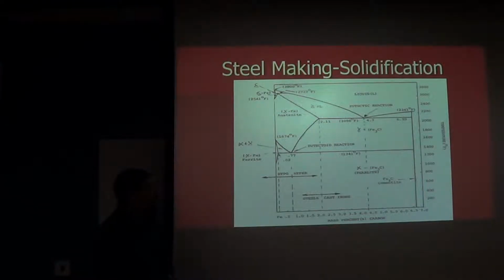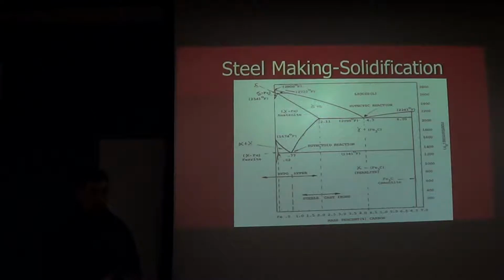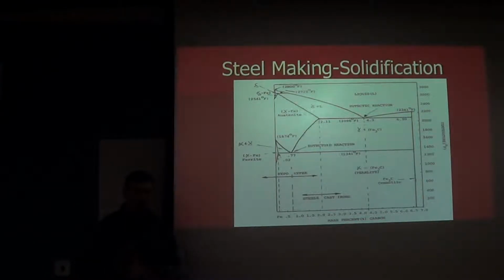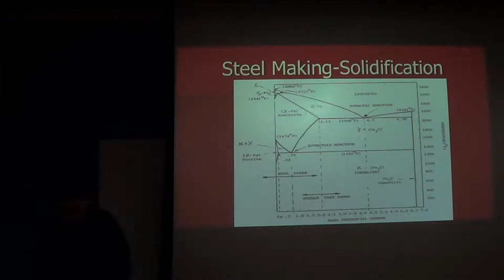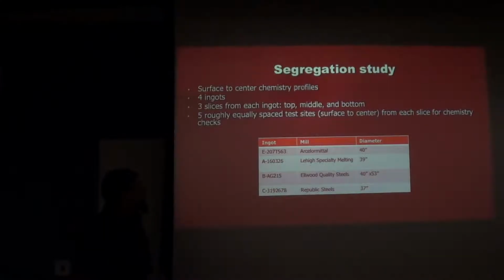So what we find in practice is that the composition of an ingot actually is quite variable depending on where you check it. How close are you to the top or bottom, or where are you through the cross section? So I had one of my former interns do a study on this, because that has application to me. You think about having variable composition, you now have variable response to heat treat, and at least the potential for variable mechanical properties. Those are all things that are important to me, making a finished good for a customer.